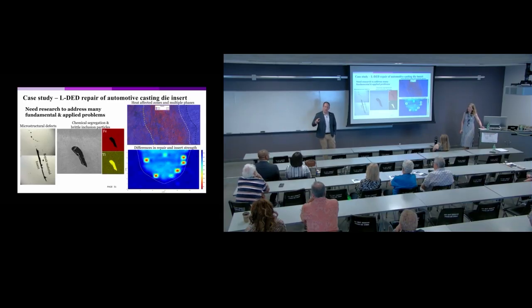So we have a difference in the printing process, which affects the microstructure and then the properties. But part of the process of making the tooling initially is they print it and then they heat treat it to get that age hardening effect. But the repair that we're looking at is just as printed. So it doesn't go through the same aging heat treatment. So we do have this, and it's a challenge, and there's things that we can do, like in situ heat treatments by running the laser more or less and understanding the thermal cycles that the material goes through. So yeah, but in this case it is the same material.